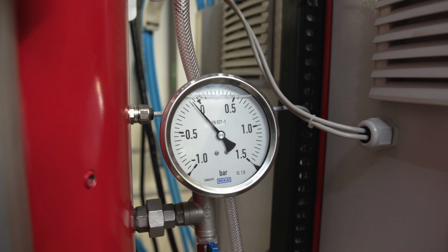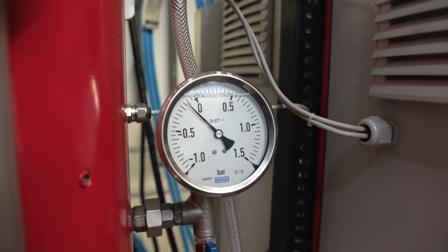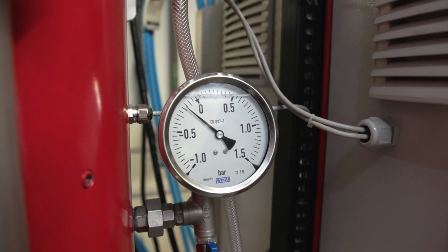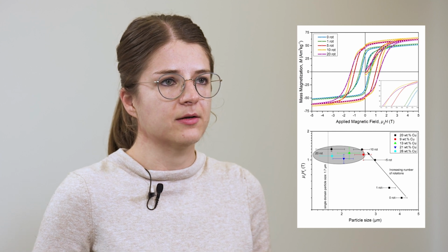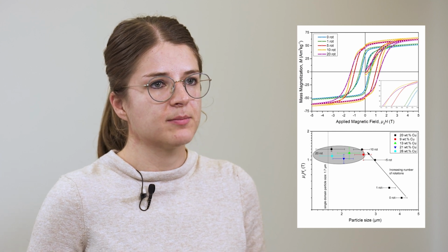So by the choice of the initial powders, we can vary the intrinsic magnetic properties. And by the process parameters during the high pressure torsion process, we can tailor the microstructure and adjust the extrinsic properties and can maximize the magnetic hardening effects. So in the end, we can generate bulk composite materials with grain sizes in the nanometer range. And recently, the process was very successfully used for the production of samarium cobalt-5 copper nanocomposites, which have promising magnetic